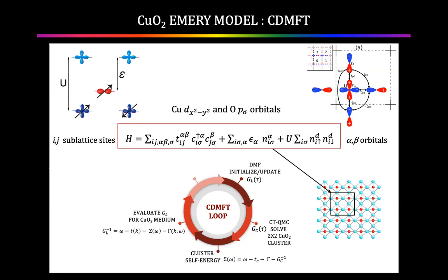Embedded in a material with hypothetical Green's functions of the same symmetry, go around in this loop, solving, typically by continuous time quantum Monte Carlo, the impurity state, find the cluster self-energy, update the Green's function, go around until it converges. If it converges, now you know your Green's functions for the whole system. At that point, you can make the following calculation. The average of this function over your sample, the anomalous average representing the superconductivity: is that number 0 or is it finite? If that number is finite, A, they call it the order parameter, and B, they say the system is superconductive. So that's the cluster DMFT machinery.